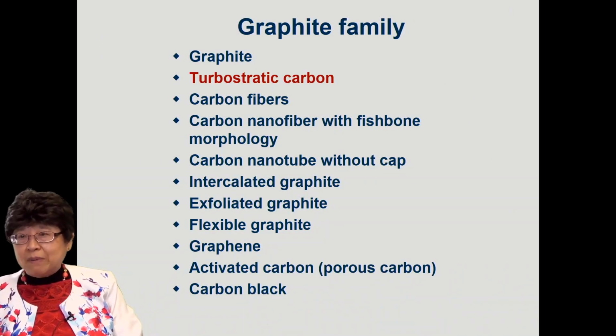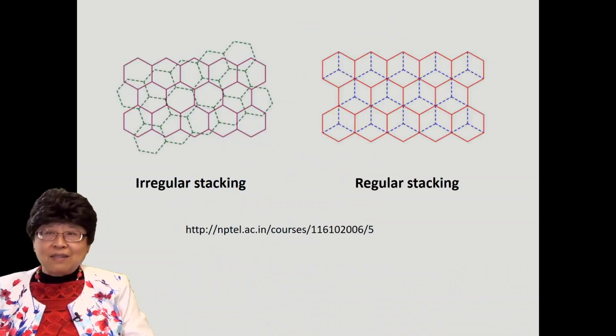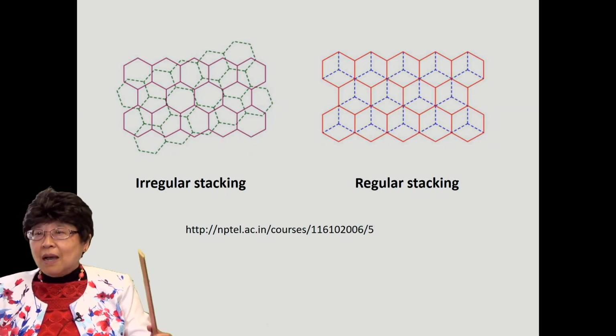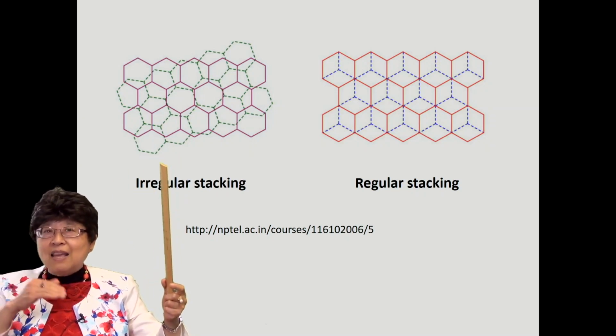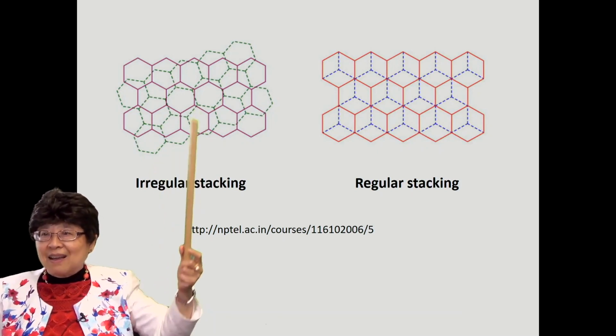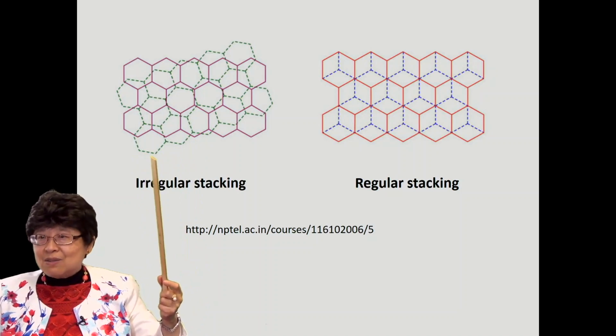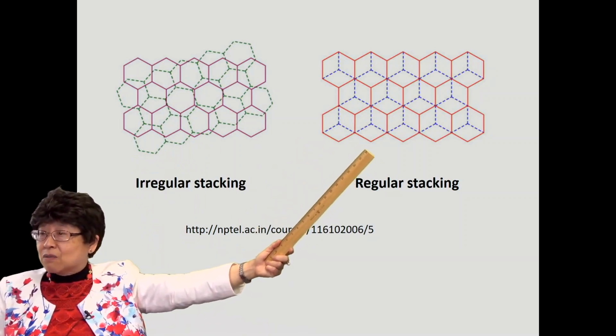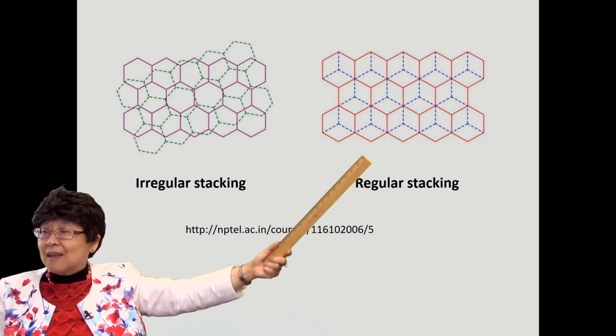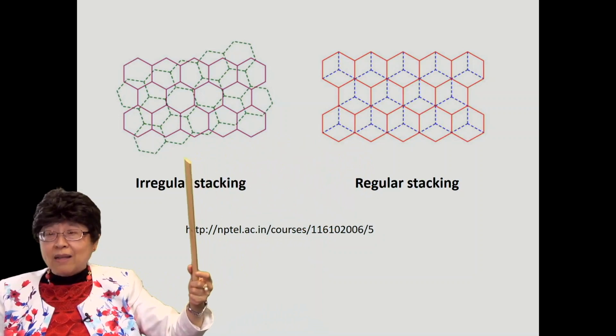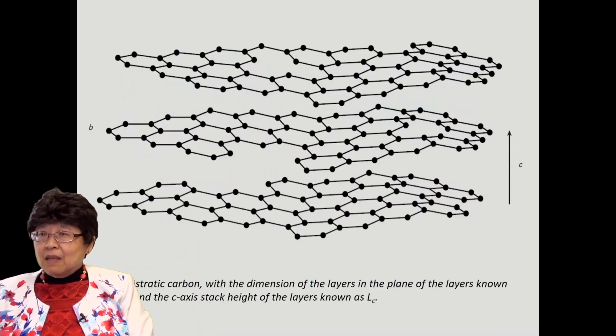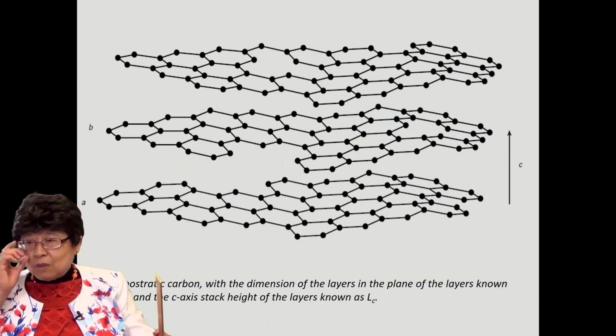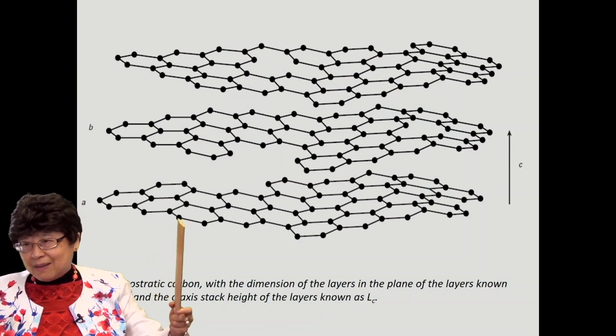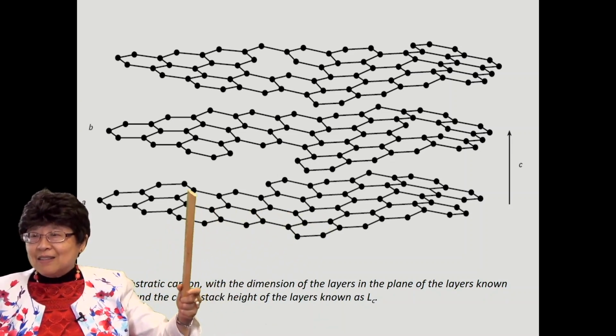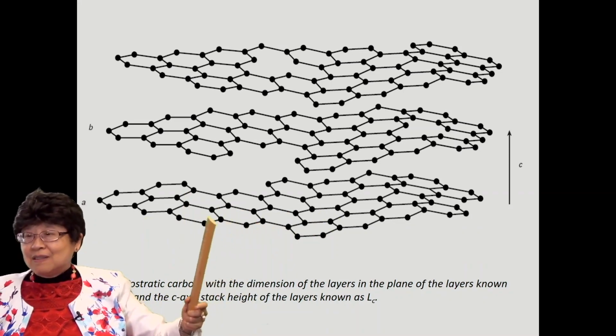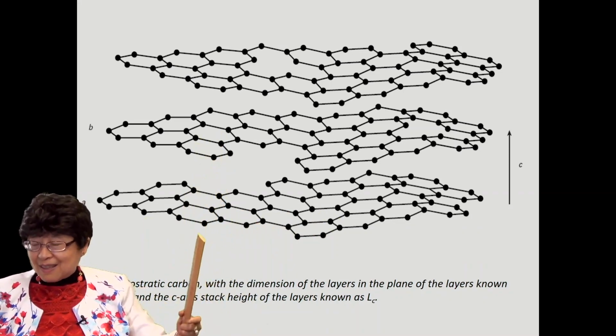Okay. Turbostratic carbon, on the other hand, is not so ideal as graphite in terms of the structure. There is irregular stacking, that is not AB, but there's no such registry between the layers. And that is in contrast to the ideal graphite case where there is regular stacking, that is the AB registry. In turbostratic carbon, there is no registry. In addition, in turbostratic carbon, the layers are not very nice. Okay? They are a little crooked. They are not very extensive, and the parallelism is also limited. Okay? But still, there are layers.